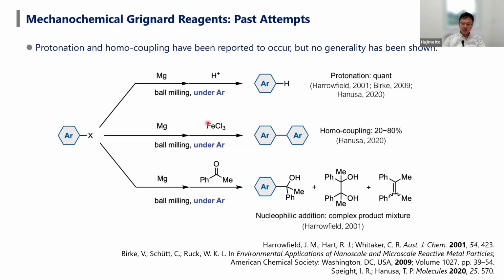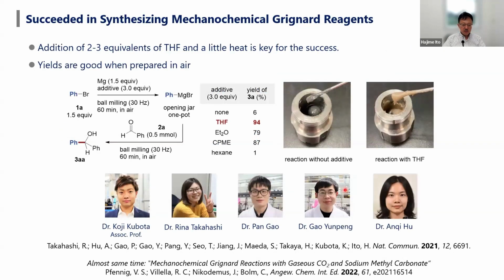Several pioneers already reported examples and trials for Grignard reagent formation using ball milling. But Harrowfield and Birke reported that only protonation was found, or homocoupling reactions occurred, and the Grignard reagent did not work very well compared to solution phase Grignard reagents.